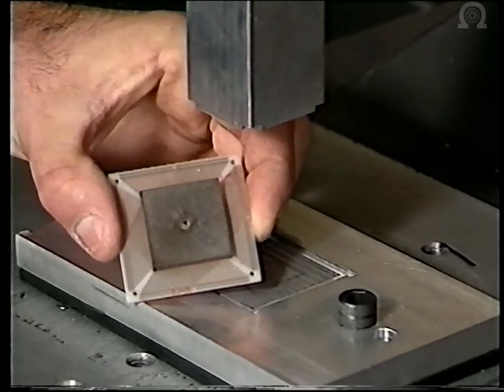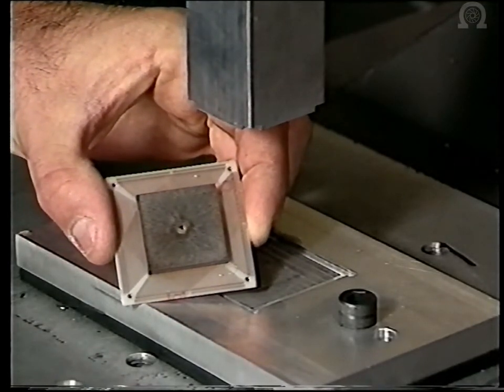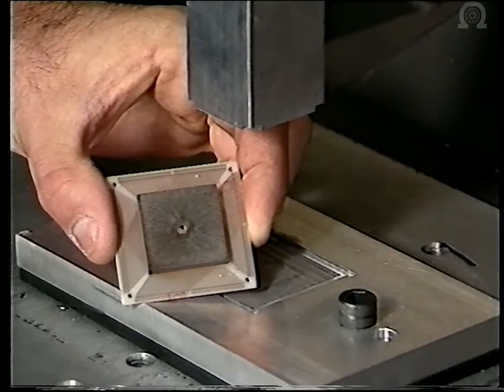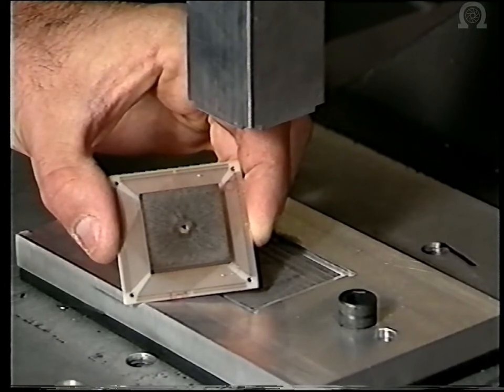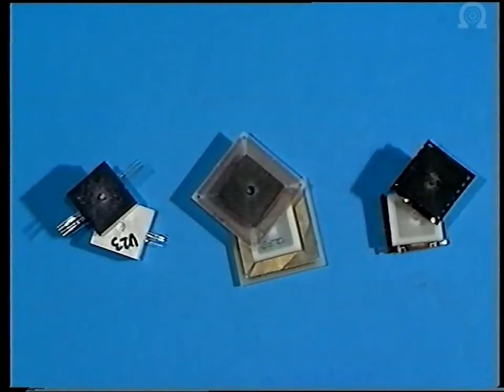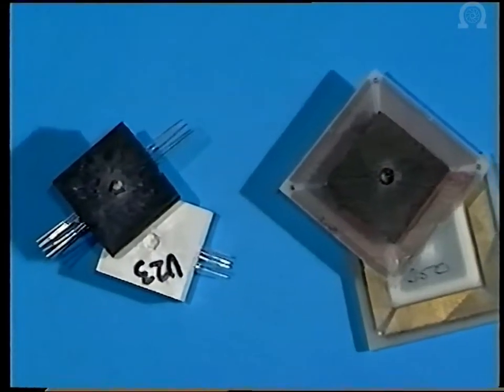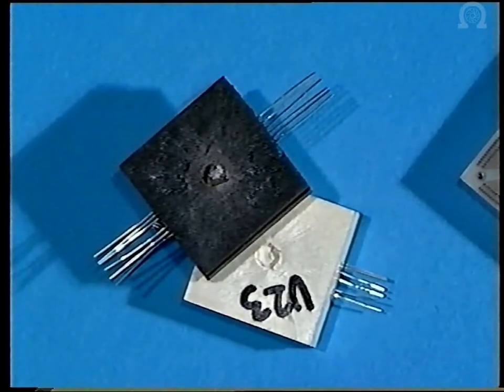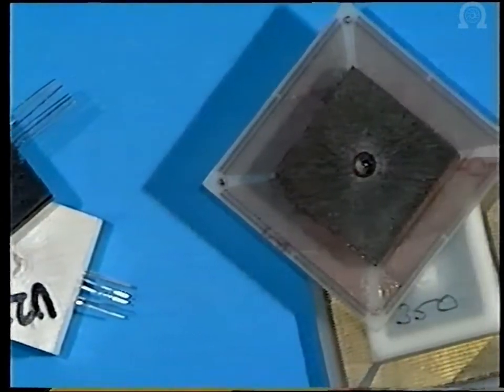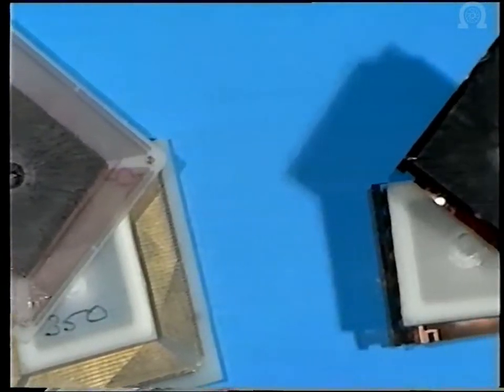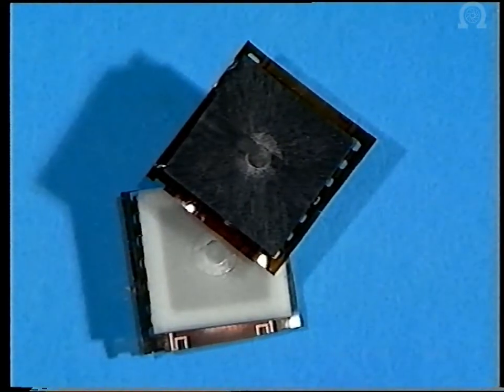In this case, the package is welded in 2 seconds using a vibration amplitude of 78 microns and a force of 600 newtons. Ultrasonic thermoplastic encapsulation has been achieved on a range of packages including lead frame, epoxy glass and polyimide PCB, polyimide tape and thermoplastic substrate.